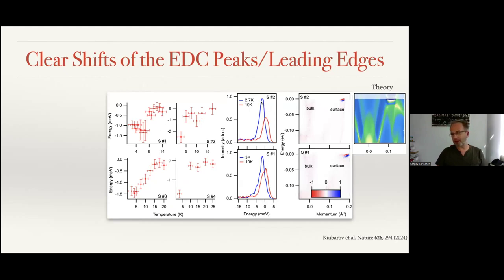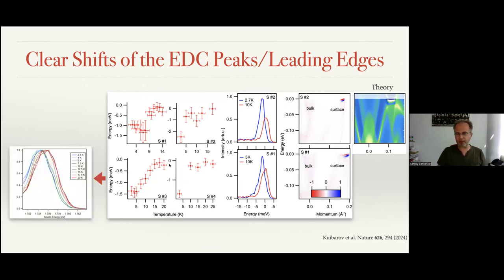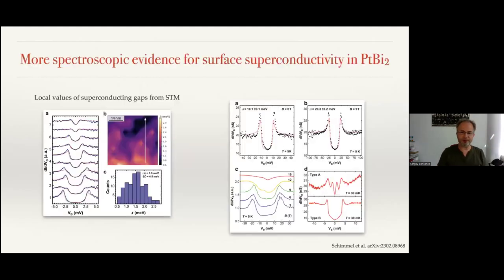So we did it in this case for several samples. We tracked the position of this peak as a function of temperature, and typically this kind of drop indicates the critical temperature. So in this case, we showed the data for 4 samples, and this is the broadest transition shown here. So this is how the superconducting gap opens. It's not big, it's a couple of millielectron volts, but this indicates the opening of the superconducting gap. And from these plots, one could roughly estimate the critical temperature. So there were around 10 kelvins for one surface and around 7 kelvins for another surface. They turned out to be slightly different.